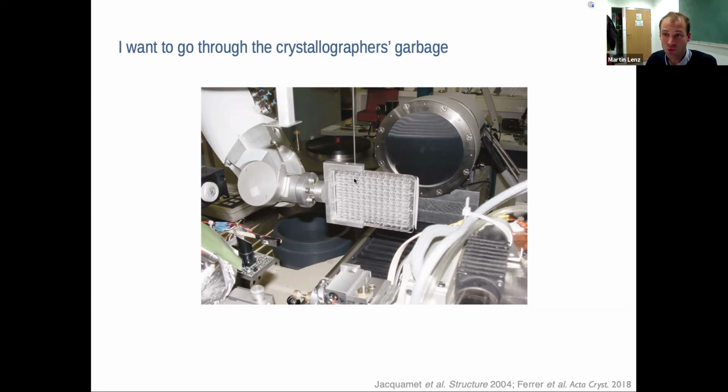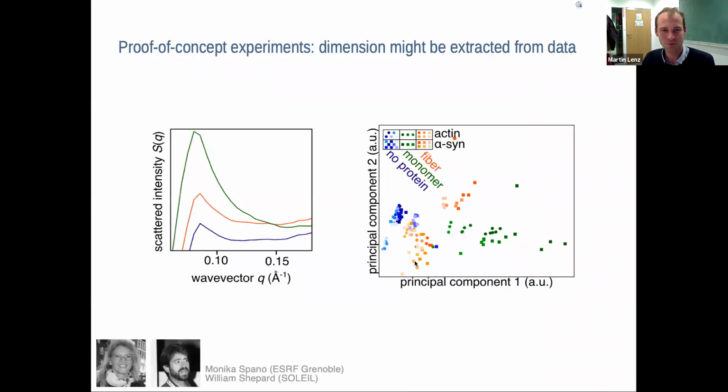But the cool thing is that what they do in modern times is that they typically try all those different conditions inside those plates, and they take those plates and they put the whole plate under the X-ray beam in the synchrotron. And so the automated procedure essentially goes through all the wells and decides, oh, this one has Bragg peaks, this one doesn't have Bragg peaks, and the ones that don't, they throw in the garbage. But those are exactly the ones that we're interested in, right? The ones that didn't form crystals. And the hope is that the small amount of information that they got from scattering off of those things that don't produce Bragg peaks might be sufficient in order to find out what kind of an aggregate you were dealing with. Now, if this was nice and clean SAXS, of course, there's standard procedures in order to infer this, but this one is uncomfortable in terms of the scattering angles that you're looking at, and so on and so forth. So it's a little bit of a challenge to try and extract the right information from them.